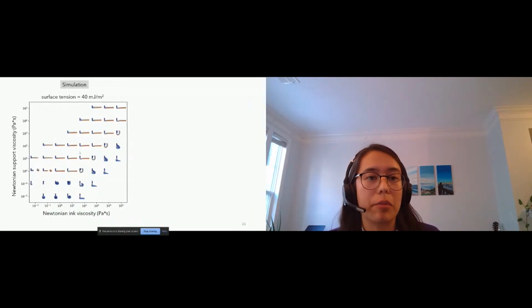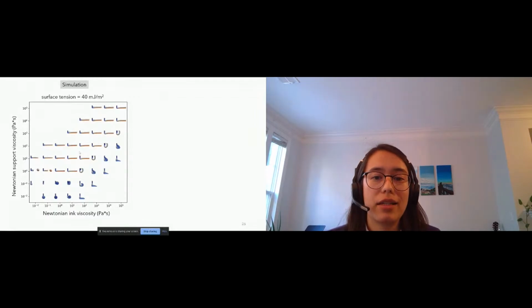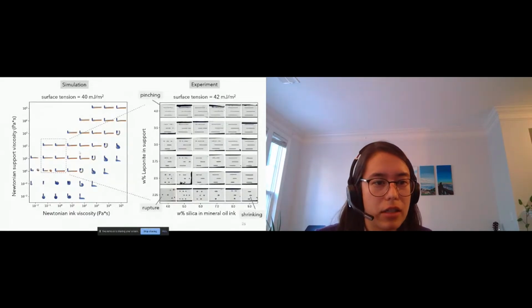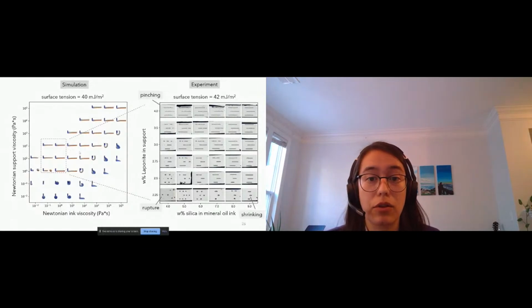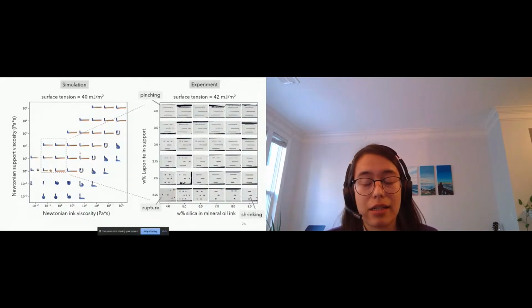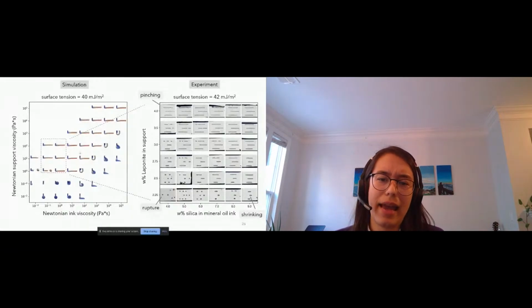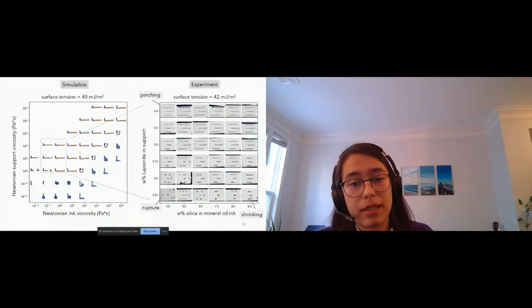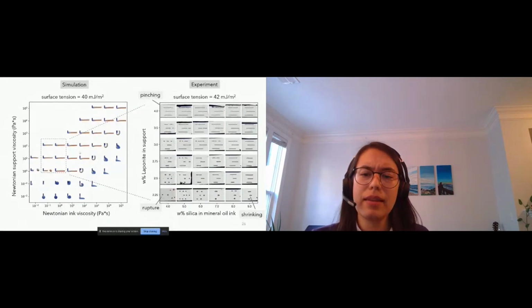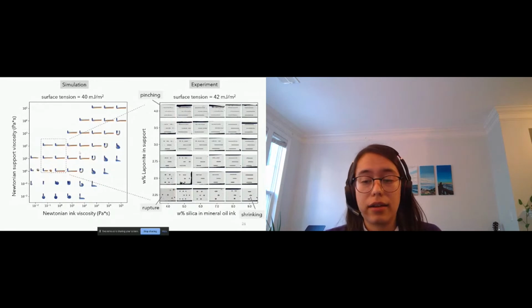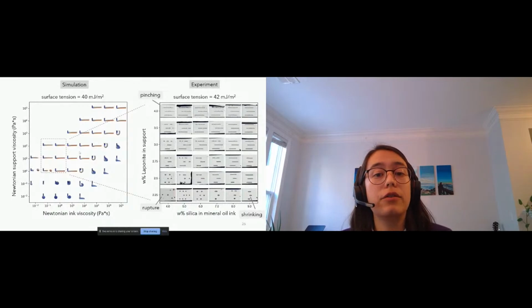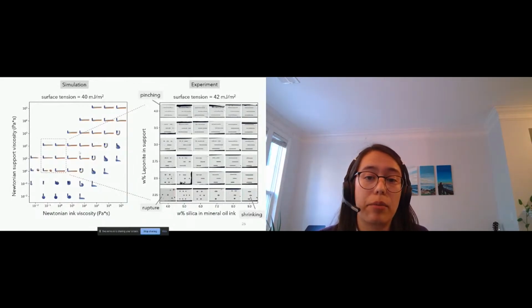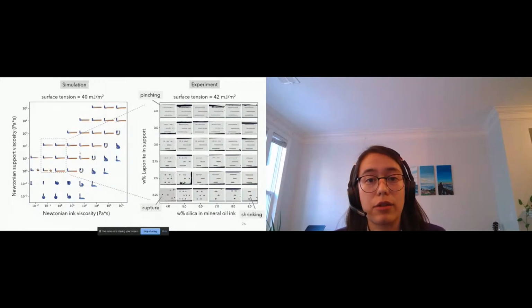a singular droplet. If we compare that to our experiments, these experiments are covering a smaller region of this viscosity map in terms of the local viscosities, but you can see we get the same pattern, where at low support viscosities, we get filaments that break up into droplets or start to go towards a spherical shape. And if the ink viscosity is low, you get filaments that break up into droplets. If the ink viscosity is high, you get a full filament that then shrinks back towards a spherical shape. If we go to high support viscosities, we suppress that breakup and we still get continuous filaments.